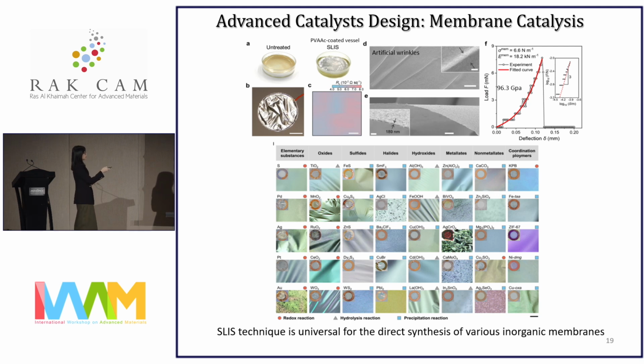And the freestanding silver membrane has a thickness of about 189 nanometers, and this thickness can be tuned depending on reaction parameters. And it has a comparable Young's modulus of about 96.3 gigapascal as compared to a bulk polycrystalline counterpart. And the other thing is that it has excellent flexibility, as seen from here, the absence of fracture in the artificially created wrinkles of a bending radius of about several micrometers.